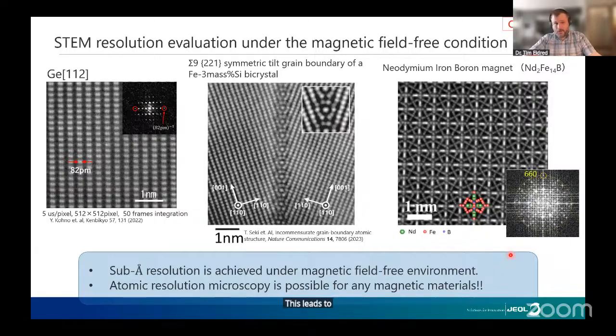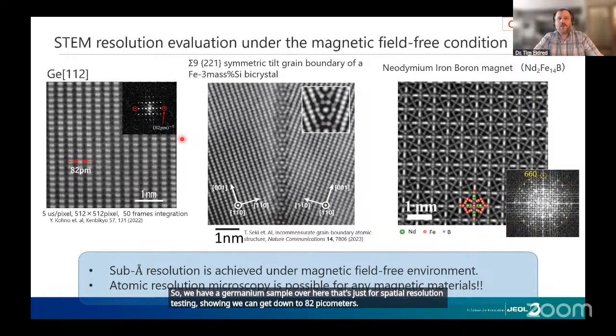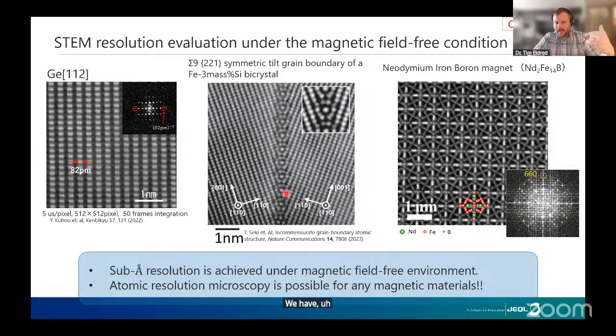This leads to imaging of materials that we were never able to do. So we have a germanium sample over here that's just for spatial resolution testing, showing we can get down to 82 picometers. We have atomic resolution images along grain boundaries, but the most important one to me is this one over here, which is literally a rare earth magnet that we're able to do atomic resolution work on. This is not something that is possible without a system like this, to get atomic resolution data on an active magnet. This allows this kind of interrogation for basically any magnetic material.